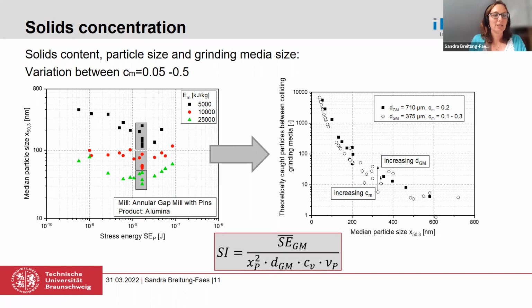Then I looked at the solids concentration, and as you can see here in the first graph, it's in principle the origin stress model run with experiments for different solids concentration from 5 to 50%. If you run these experiments, you get for each concentration a certain median particle size for a certain specific energy. This can be seen here in the gray boxes. And we have to summarize here that if we want to use the origin stress model, we need for each concentration a separate curve.